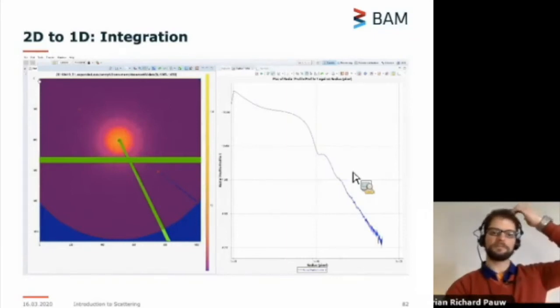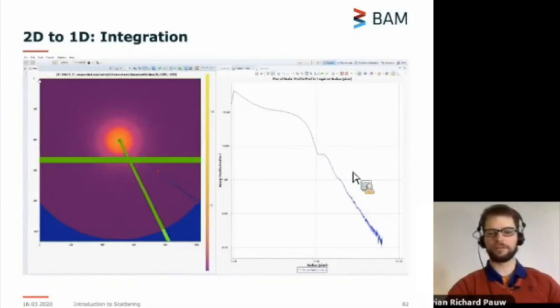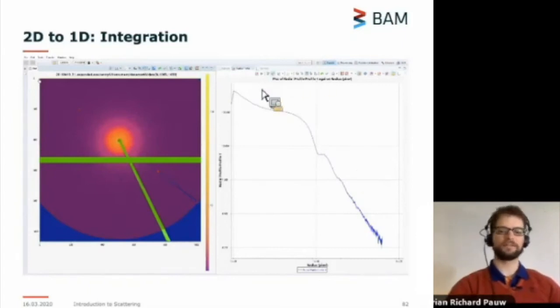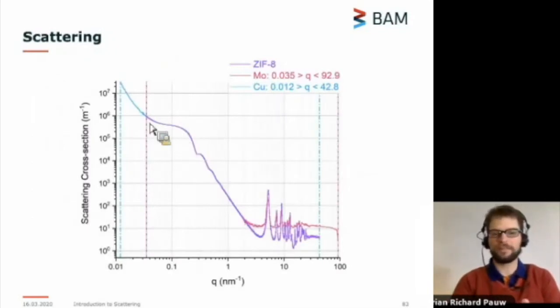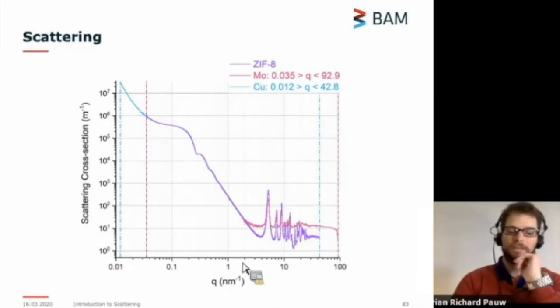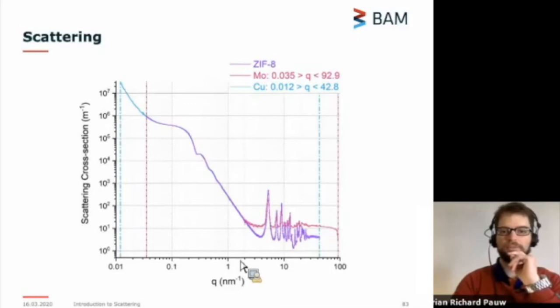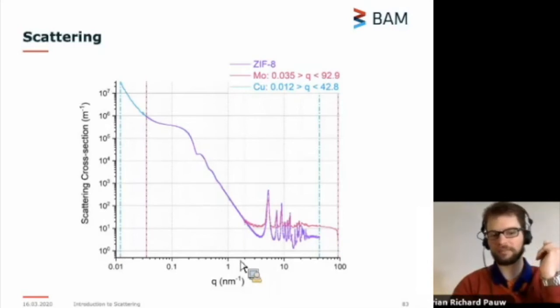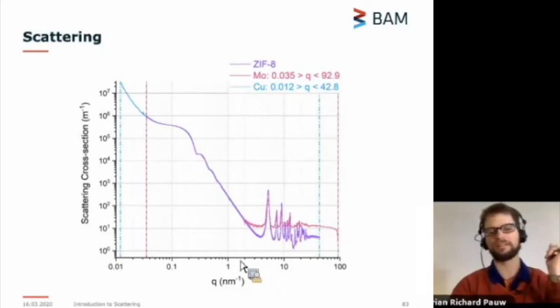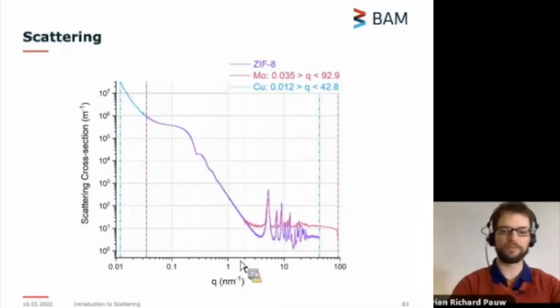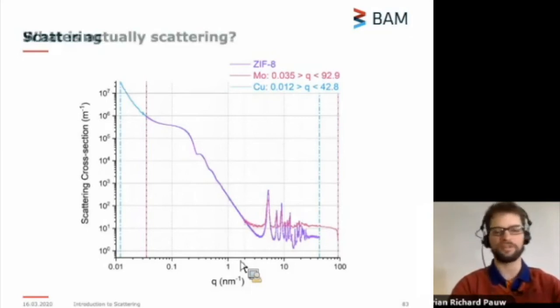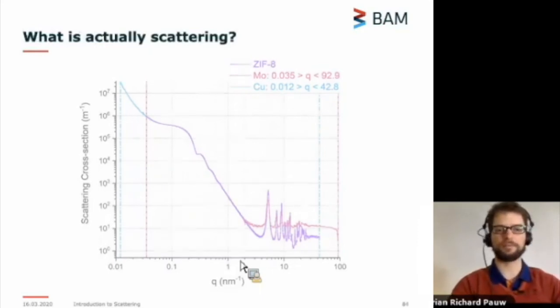All right, so if you're then finished with collecting this information, you might get a pattern like this. This is a scattering pattern from a ZIF-8, a metal organic framework that was synthesized and measured by my colleague Glen Smales. We measured this with two sources, a molybdenum source and our copper source. These have slightly different ranges. But we measured this in total over almost four decades in size. Over here it's indicated as Q, but Q is a description of angle. But this really represents four decades in size information.